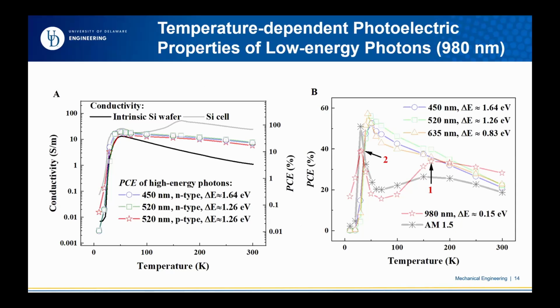However, we also tested low-energy photons, as I mentioned, this infrared light, and its behavior is a little bit different from the other three, high-energy photons. For the other three, decreasing temperature increases efficiency, and then it comes down. For the 980, you can see this red curve has two peaks. One is from about 150 to 200 Kelvin. This is exactly what people found before, and it is dominated by the dopant elements. So this is one peak.